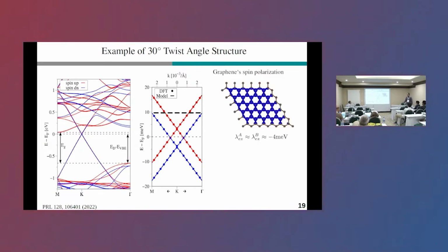If you place your Fermi level at this dashed line and you calculate the spin polarization that is on graphene, you will find it to be very uniform and negative. And the corresponding model parameters are the same for both sublattices and also negative. Now, where does this come from?